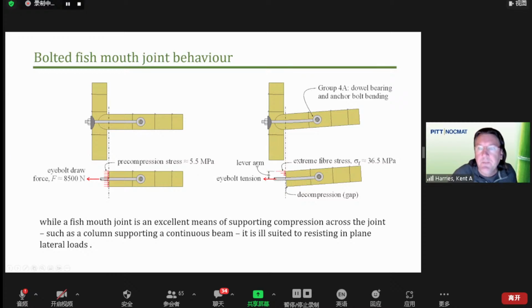As we start moving this back and forth, we have different types of behavior. We have dowel bearing type behavior, particularly at this location. And it's interesting because if we look at our ultimate stress condition, we would have tension in the eye bolt, compression at the top or bottom fiber of the joint, and opening at the opposite side. And when we calculate the extreme fiber stress, in this particular case, we had about 36 MPa, and that's where I want to bring you back.